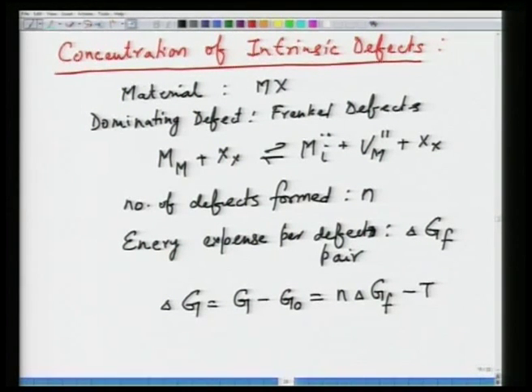Because the moment you create the defects inside a material, it is going to lead to a change in the configurational entropy, which is delta SC, and which is going to be a positive quantity because you are going to introduce defects, which means you introduce disorder inside the material, and as the disorder increases, the entropy always increases. So this is the basic thermodynamic free energy change that is going to happen when you form n Frenkel defect pairs, each defect pair having energy of formation of delta GF, and minus of that entropy term, which is a positive term because of increase in the entropy.